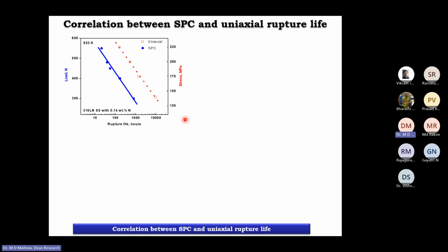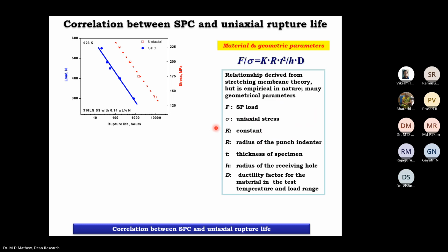Now, how do we correlate the small punch creep data with conventional creep data? See, this graph shows the data from the uniaxial test, stress versus rupture life. And this is the data from the bending test, rupture life versus load, while here it is stress versus life in the uniaxial data. Now we have to find some correlation between the uniaxial stress and the SPC load. So this is the kind of relationship that has been generated between F, that is the SPC load, and sigma, the uniaxial stress.